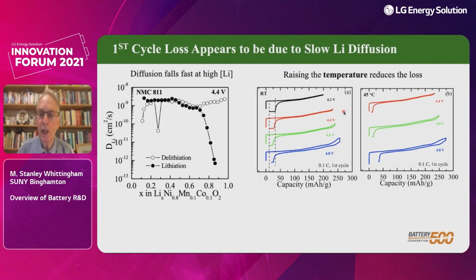So to prove to ourselves that diffusion was probably the rate controlling step here, we looked at raising the temperature. So this shows that same data now at four different charging voltages. We charge up, in this case, to 4.2 volts, take it back to 2.8, then hold it there for a few hours, and you can see we get some of the capacity back. Clearly diffusion control. Same at 4.4 volts, comes back to about the same position. At 4.6, we're getting more capacity, 4.8, even more. But now you're seeing the charge and discharge curves are separating.